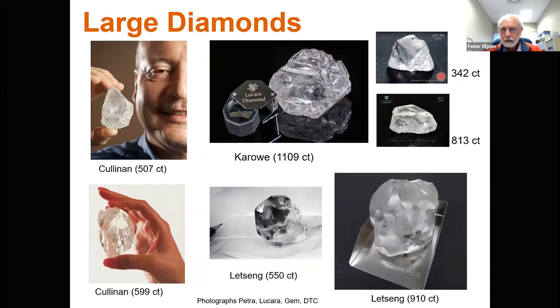When they are not damaged, they have these very unusual potato-like shapes, and many of these large diamonds do contain low to no nitrogen. So I would imagine that much of the shape that you see here is due to resorption in the kimberlite, but the resorption is assisted by the low nitrogen content of these diamonds to give you these unusually smooth, rounded off morphologies.